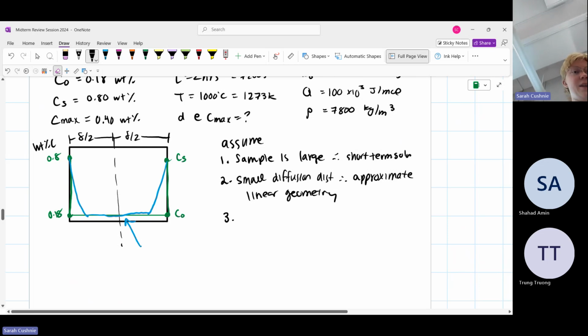Another assumption that you can make, again, these are just assumptions that had been brought up in tutorial and I'd written down on my formula sheet or cheat sheet to make sure that I remembered to say so I didn't lose any marks. So another assumption that we can make is that it's immediate diffusion. So no incubation time. Sometimes for certain reactions, let's say you put this hunk of steel inside the carburizing furnace, it'll take a little bit to heat up to the temperature of the furnace, right? To undergo that diffusion process. And that means that you wouldn't actually get the same amount of diffusion as you might calculate here, because you have that time at the beginning where it's not actually diffusing. And we're just going to assume that doesn't happen.